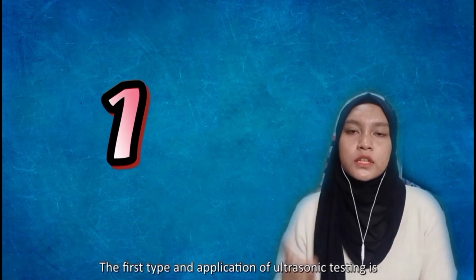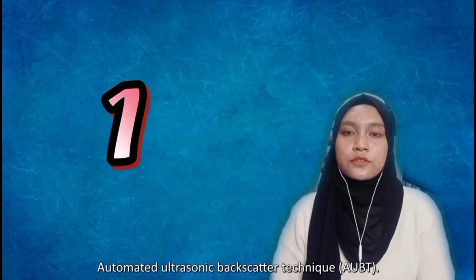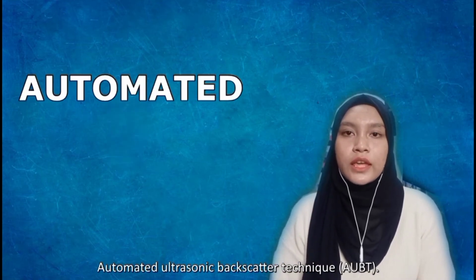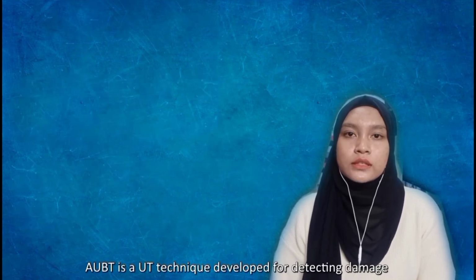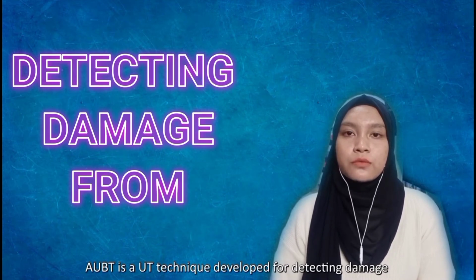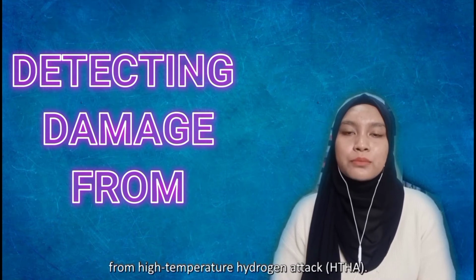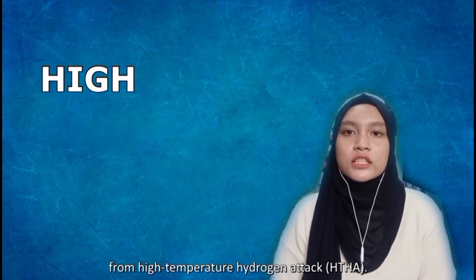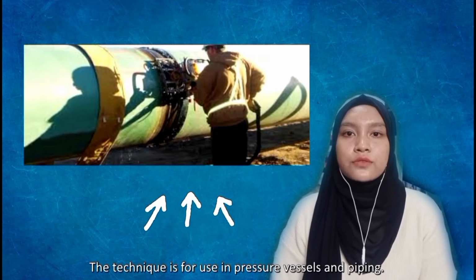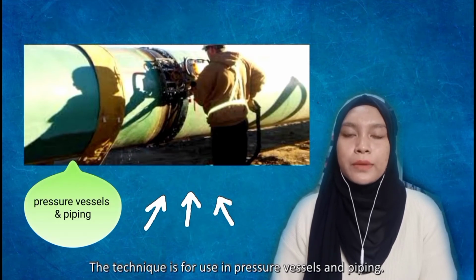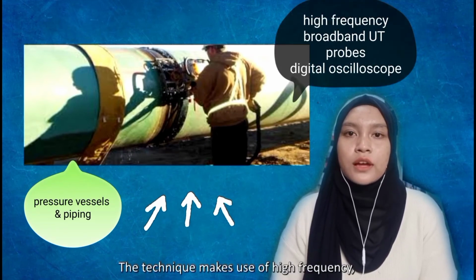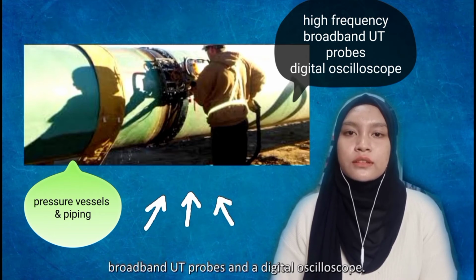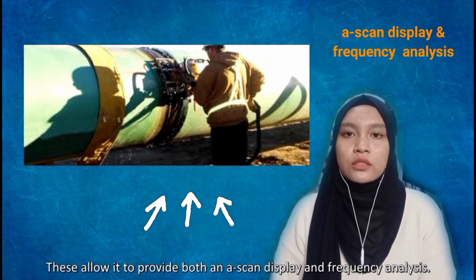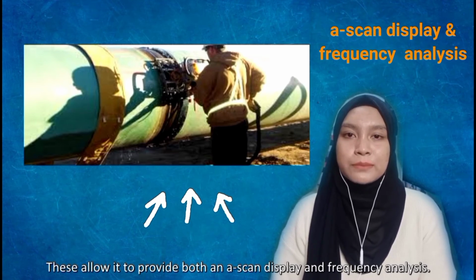The first type and application of ultrasonic testing is Automated Ultrasonic Backscatter Technique (AUBT). AUBT is an ultrasonic testing technique developed for detecting damage from high temperature hydrogen attack (HTHA). The technique is for use in pressure vessels and piping. It makes use of high-frequency broadband ultrasonic testing probes and a digital oscilloscope. This allows it to provide both an A-scan display and frequency analysis.